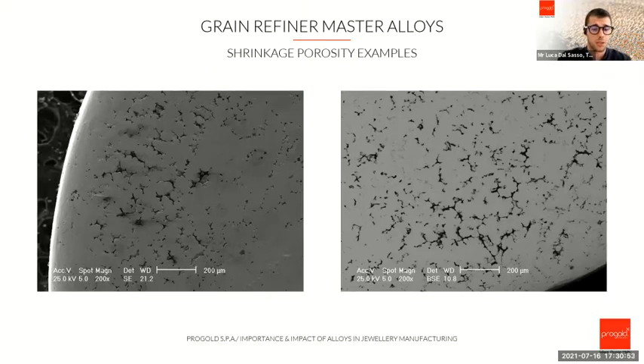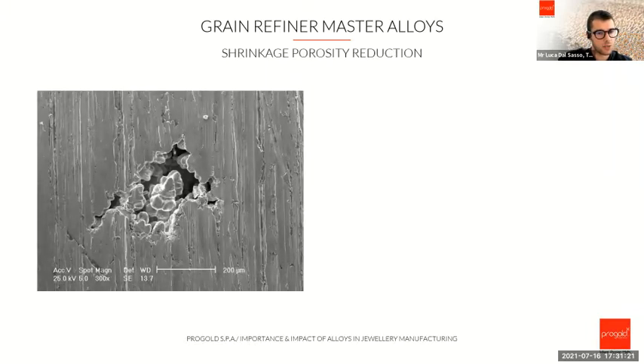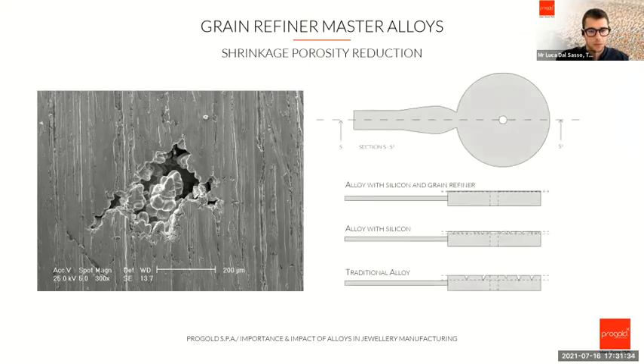But when this shrinkage isn't homogeneous on the surface, it can be bigger on a precise spot, and it's there that we have the deep pores. So the exact spot is where the shrinkage is bigger. Now we can go on with the next slide and see what the shrinkage porosity looks like in the microscope view on the left side. And on the right side, we're going to see how ProGold has chosen to react to this problem. We started from this metal.